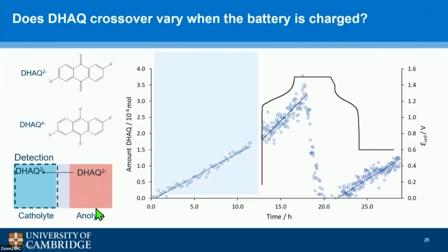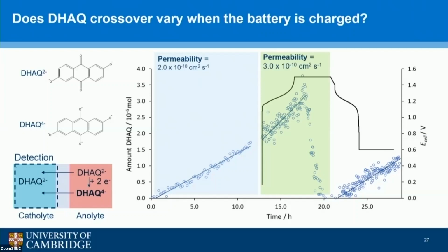So at the start, we're just looking at quinone crossing over just as normal, and we're detecting it in the catholyte side. And from this, we can then calculate a permeability just as before. And then in the second part of the experiment, we are now charging to the 4- state. And at the start, you see we can get a permeability.